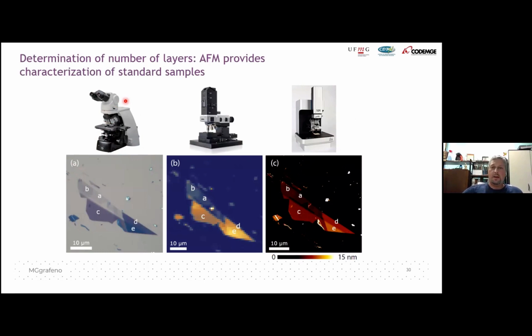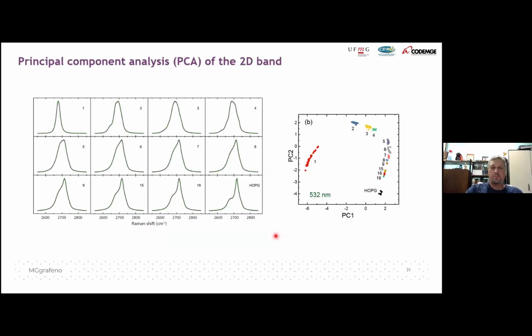And here what we did, we characterized a lot of Scotch tape graphene. We made Raman maps and AFM. And we built a group of around 100 pieces of graphene from standard samples, the Scotch tape samples. We measured a lot of 1 layer, 2 layers, 3 layers, and we built a library of this type of standard samples. And we did something called principal component analysis, which is basically a software